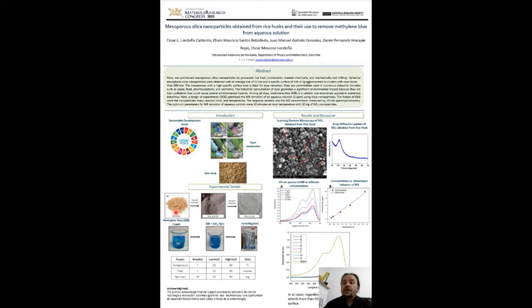To prepare the rice husk ash, the husk was washed four times with distilled water to remove impurities and contaminants, and it was dried in the oven at 100 degrees Celsius for 3 hours. Subsequently, it was taken to the oven where the temperature was raised at a rate of 5 degrees per minute until it reached 500 degrees Celsius, and it was kept isothermal for 1 hour to eliminate organic material.